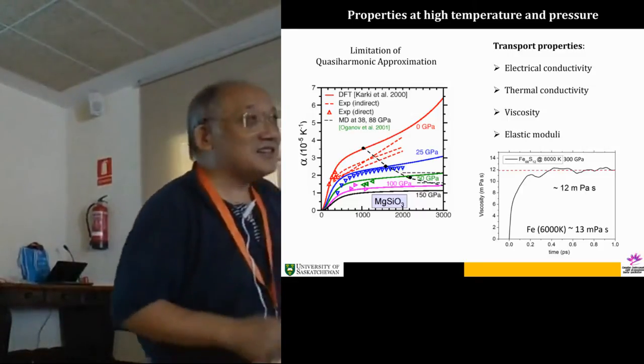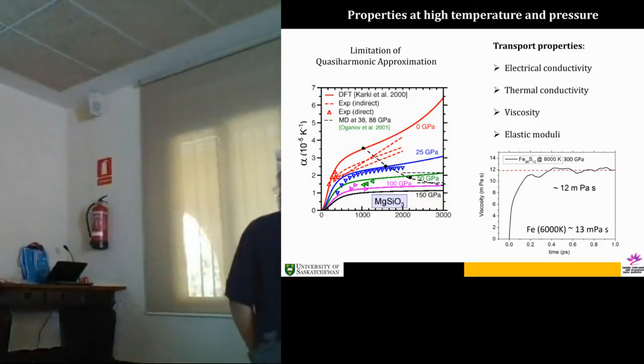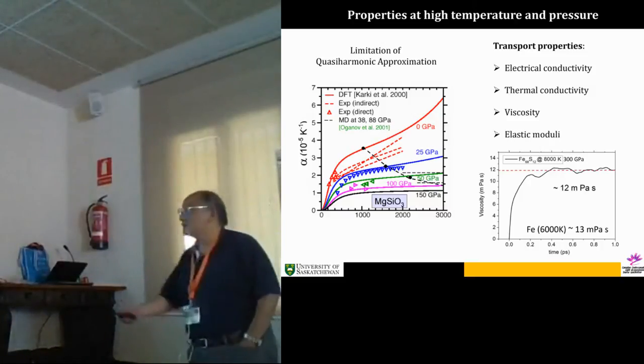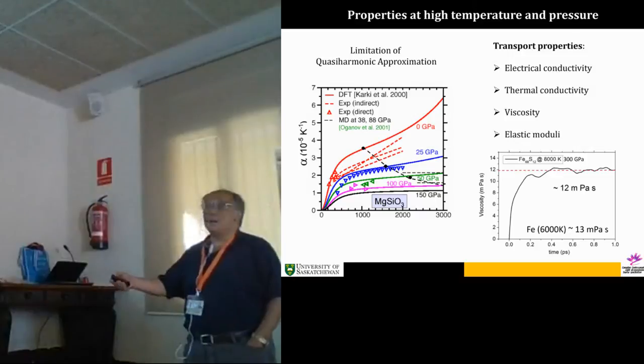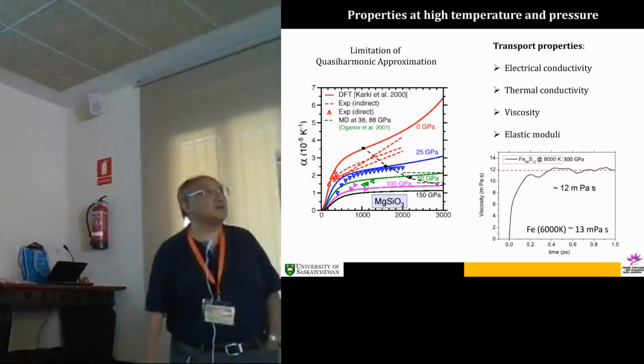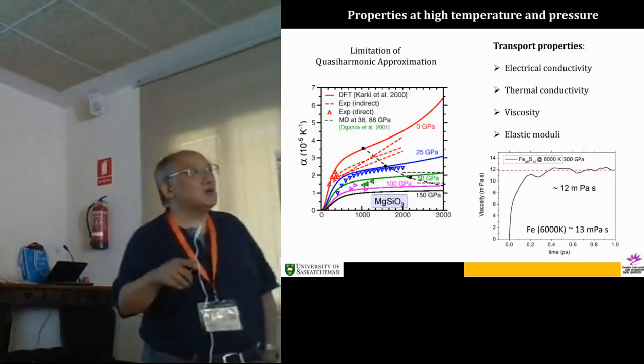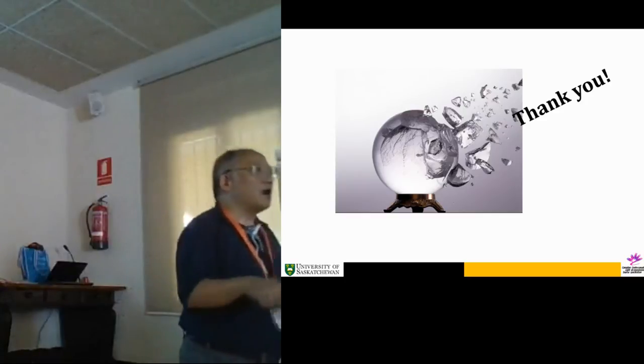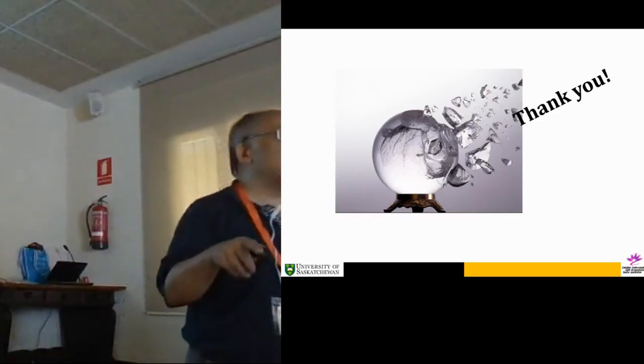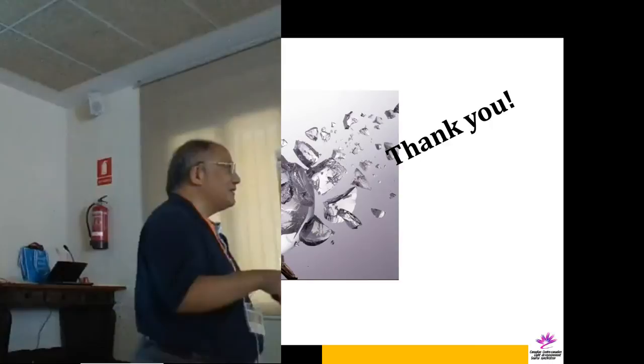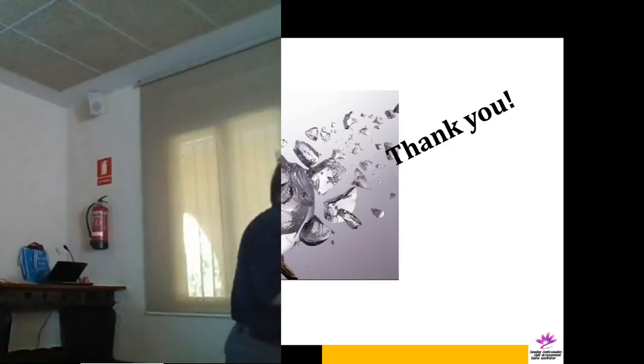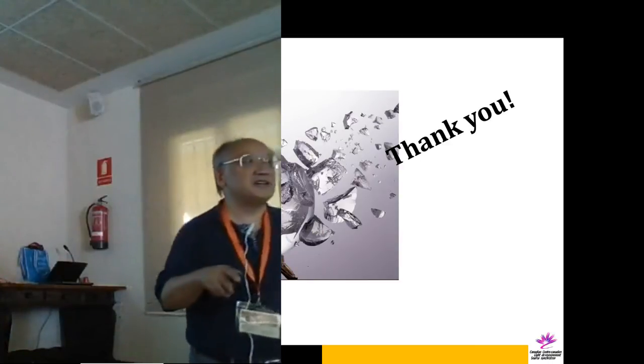Another thing is high temperature. We talk about temperature, and we comment on how accurate the calculation is. A lot of people just use the quasi-harmonic approximation. The quasi-harmonic approximation is a problem. You have to understand what the Debye temperature is. Normally, the rule of thumb is that at about 3 times the Debye temperature, it will deviate.